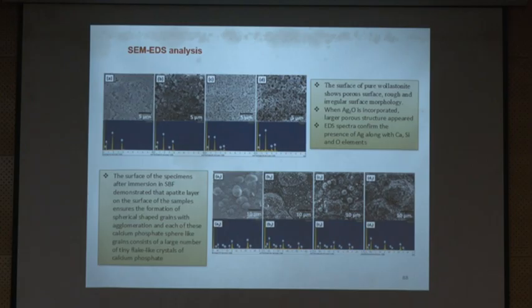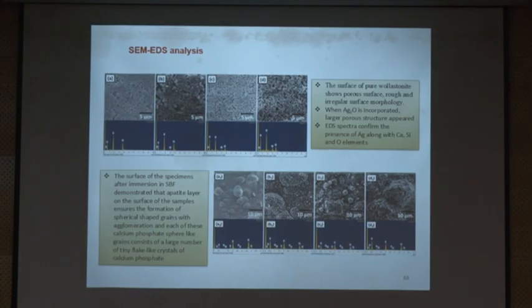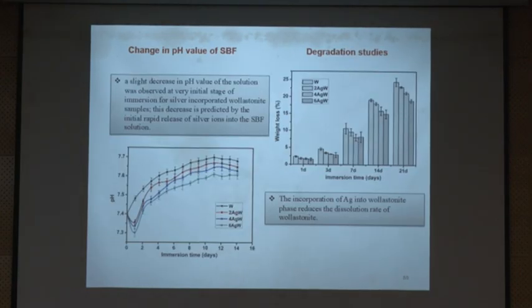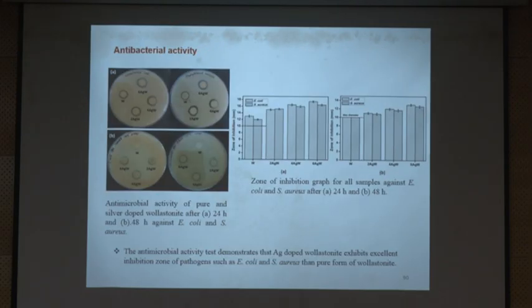So what actually is happening here is that there is a leaching of ions between your material and the SBF, right? Because of that there will be nucleation centers around which the material tries to grow, and with time it will expand throughout the surface, and the thickness of the layer also increases, and it is spreading throughout the surface, which was already shown in the previous image. So similarly, you can confirm by means of variation in the pH value, weight loss also, and this is the important test people perform to check whether the material is bioactive or not.